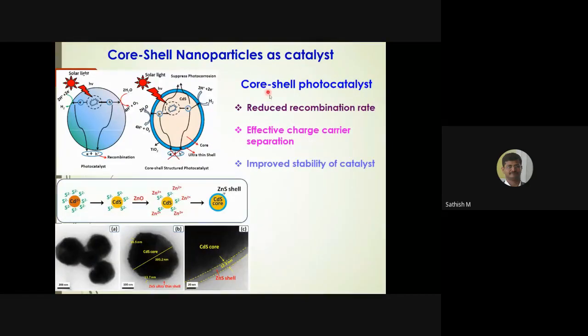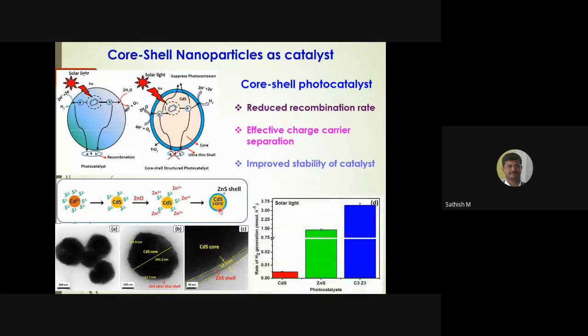So we have also prepared various systems. As I told you, the cadmium sulfide based system, and over there the zinc sulfide based system. Here the point is the zinc sulfide has a band gap of 3.8, so it will not absorb light in the visible region. So there won't be any photo corrosion in the case of zinc sulfide. Whereas the light is absorbed by the cadmium sulfide, but the cadmium sulfide is in the core. It's not allowed to react with the solution, so it will not undergo any oxidation or reduction reaction. Its job is only to get excited and then give electrons and holes to the zinc sulfide system.